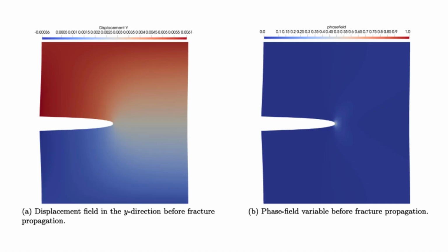Okay, hit me with it. What was the peak iteration count there? Using their recommended smaller time step, delta t = 0.01, at the onset of crack propagation in the notched plate, the AM algorithm needed a peak of 405 iterations to converge. 405 iterations just to calculate one step forward in time as the crack starts. Wow. 400 loops of solving displacement, then solving damage.